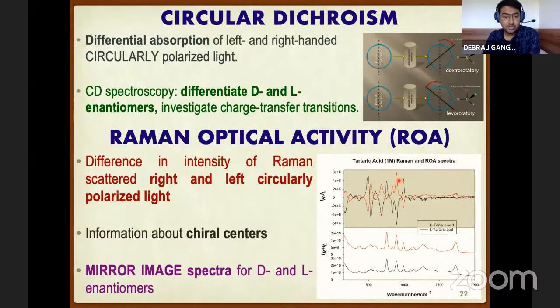The positive peaks show us that the IR is stronger than IL for those particular vibrations, and the negative peak shows that the IL is stronger than IR. But the important thing which we observe in Raman optical activity is that when we take a dextro and levo, or the two enantiomers of the sample, we get mirror image spectra.